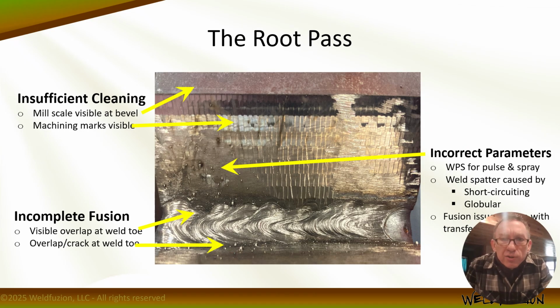During a process inspection, monitoring revealed the following situation. There was insufficient cleaning of the base material. Note the mill scale and visible machining marks. There was no indication that the mill scale was cleaned to an acceptable level around the joint, and no indication that the coolant and fluid that may have been used for machining was cleaned or removed from the weld face. Incomplete fusion occurred in several areas because of poor welding technique and maybe incorrect parameters, right?